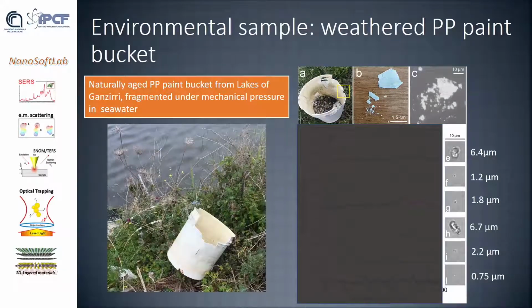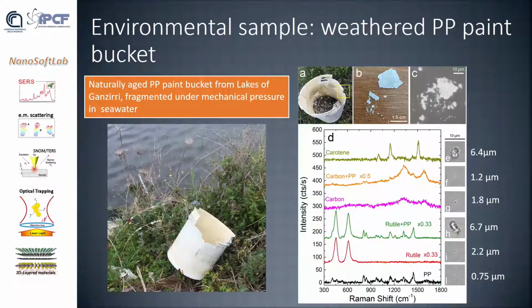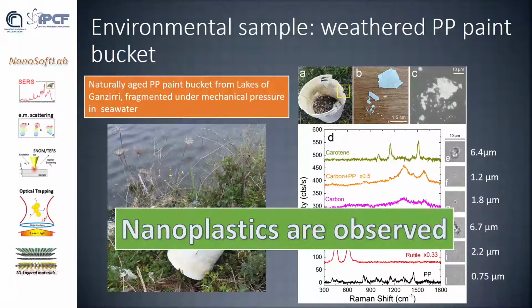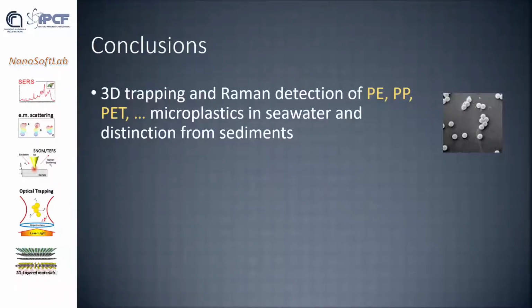If we do this in water, for example if we break this on the lake, we will disperse this kind of material into the water, and we can trap them one by one and discover their chemical nature, ranging from polypropylene, rutile - basically the materials composing the paint. So again, the message is that when we break brittle materials, we can produce nanoplastics, and if we break these materials in water, we can use optical tweezers and Raman tweezers to trap them one by one and analyze them. With this, I conclude.